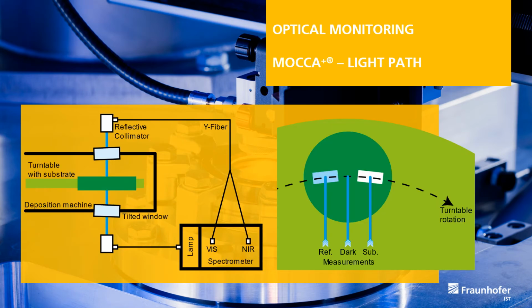On this slide, you can see on the left a sketch of the light path beginning from the halogen lamp via fiber to the reflective collimator. Then, as an open light beam through a tilted window, into the deposition machine. In the rotating turntable is an opening for the reference. You can see this in detail on the right. The further way is similar, but the light is split into 2 spectrometers by a fiber with 2 arms.